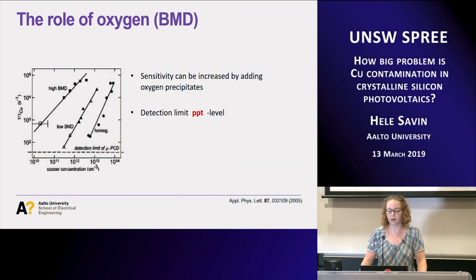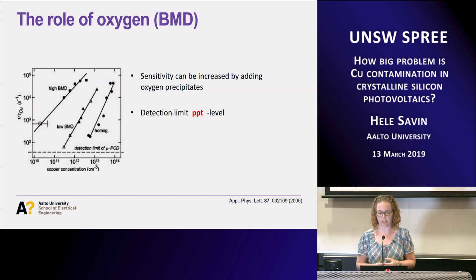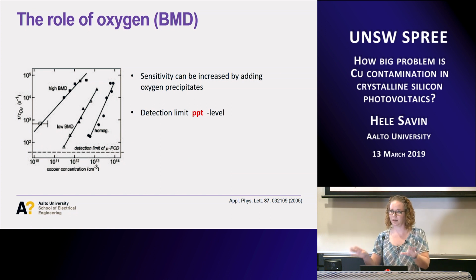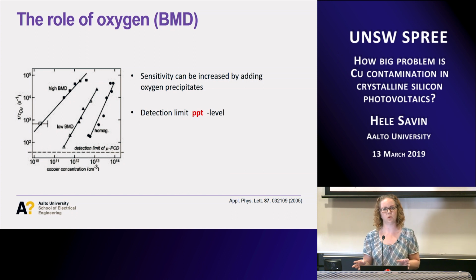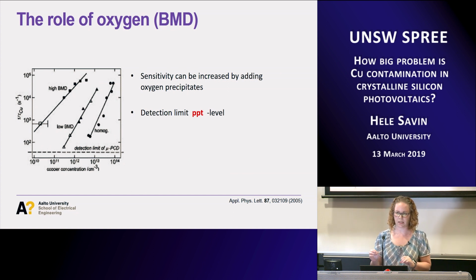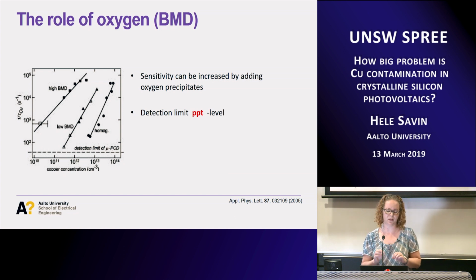Then we come to how to make this method even more sensitive. We want to go even lower in the sensitivity. We have noticed that oxygen plays a big role in copper LID. Especially I'm talking now not about interstitial oxygen, but more small oxygen precipitates, which are often also called bulk microdefects. These defects are still so small that they don't kill your lifetime. You may know that if you have too much oxygen and you make too large oxygen precipitates, then they start to be visible already in your lifetimes. But now the key is not to make them so large, only to make a high density but small enough so that they don't cause any recombination, but they enhance this copper LID reaction.